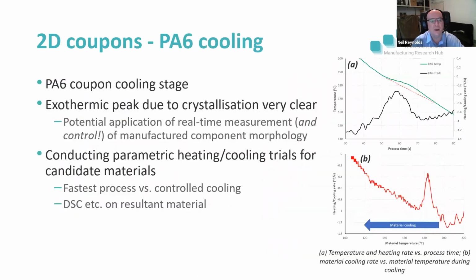So if we move to the next slide, we've done the same analysis on the polyamide material, a semi-crystalline material, and you can see the data from a cooling stage on the right hand side, where we've got in green temperature versus time, but the black line shows the actual cooling rate versus time, and effectively the cooling slows down during that crystallization stage, and you can see the onset, peak and end of crystallization. Replotting that data, as you can see in the bottom right hand side, it's almost like a DSC trace for those who are familiar, where you're plotting temperature versus cooling and heating rate, reading from right to left. So as the material cools, you can see the onset temperature, the peak crystallization temperature for that particular cooling rate, and then the end of crystallization, at which point you could demold the material.